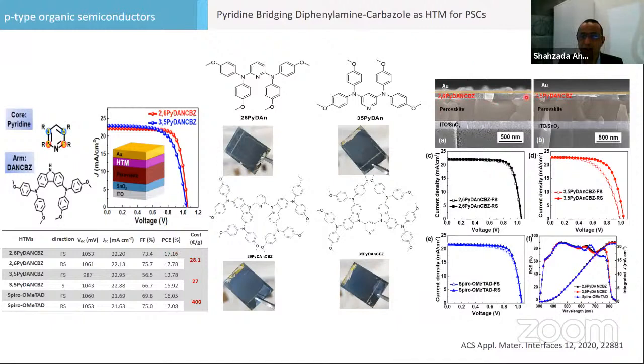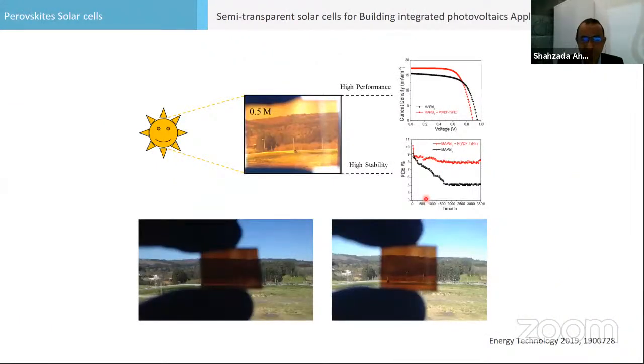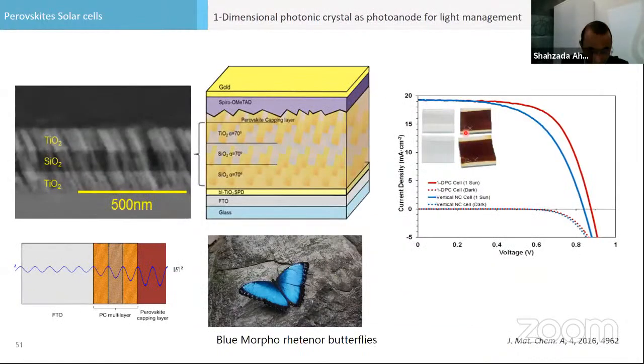Every thin layer goes to 100 nanometer for this type of materials. For building integrated photovoltaic applications, we are also studying transparent, semi-transparent solar cells. By purpose, we are making a 100 nanometer thin layer of the perovskite, so you can see through the window here, and this is also giving you 10% or 12% efficiency. We put a dielectric polymer, PVDF, to make them more stable, so that it can act as a binder and increase stability.